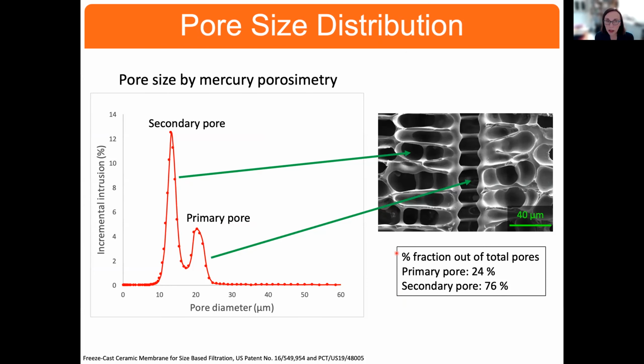And this is what one would typically see from an analysis by mercury porosimetry, in which we are plotting here the percent intrusion of the mercury for a given pore diameter. And we see here that at the larger scale, these are the primary pores, those primary channels. And these are the secondary pores, these side channels. And you see from a fraction of pores that the secondary pores take up much more space in the material. It's 76% of the pores are the side arms, where 24% are the main channels.